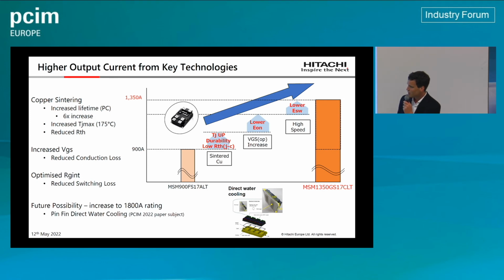Second, we are increasing the VGS operation. Previously we were recommending a 15 volt operation. If we increase that to 17 volts, we see good impact both on reducing the conduction loss and also reducing the turn-on loss. I'll show you some more on that shortly. And then we've also optimized the internal RG to make this a much higher switching speed device.